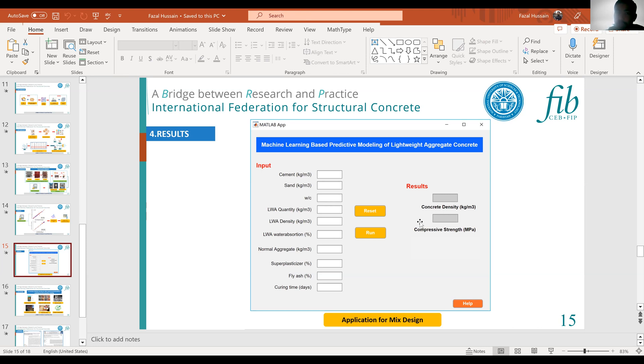The dataset includes 24-hour water absorption of aggregates. The literature reports different types of lightweight aggregate — sawdust, expanded clay aggregate, and others — all with different water absorption values. The collected dataset includes almost all aggregate types along with their water absorption. In the lab, 24-hour water absorption of expanded clay aggregate was measured, and it was found to be mostly around 10 to 12% of the aggregate's weight.